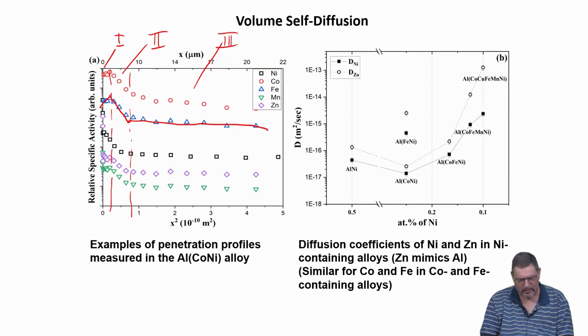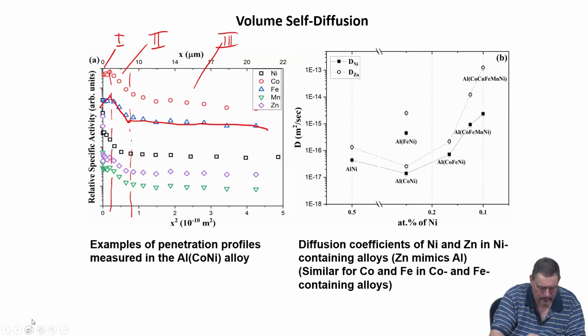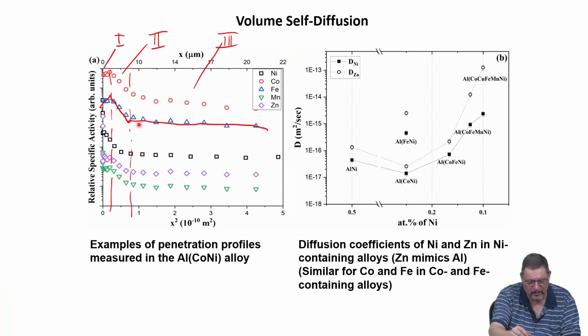Right? There's one thing which also looks a little bit strange, which is the very flat penetration profile towards long distances into the sample. So it's almost no slope, which means that in this region, the slope is very small, and that means the diffusion here happened really fast, right? Because the concentration for long distance, I mean more than 20 micrometers or so, is almost not dependent on the penetration depth. And that is basically indicating that the diffusivity is quite large.